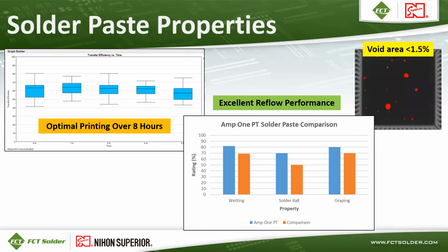And then, of course, voiding is also a concern. AMP1 PT is one of our AMP1 series of solder pastes, which are ultra-low voiding solder pastes. On this particular QFN component, the void area is less than 1.5%, which is important for anyone who has issues with voiding. I'm hearing more and more limits being applied to voiding of 25%, sometimes 15% for really critical devices, and that's challenging. If you're having a voiding problem, there are lots of different ways you could approach it, but switching solder paste is one of the things you can change in order to reduce voiding in your solder joints.